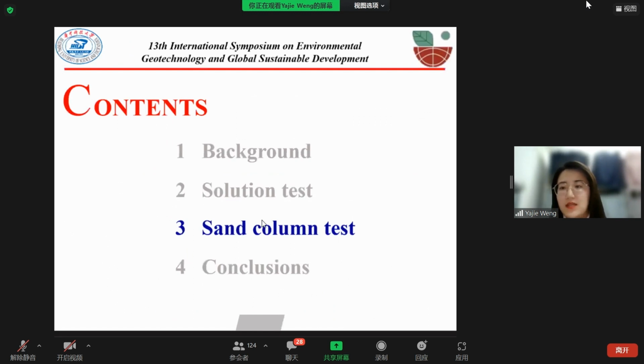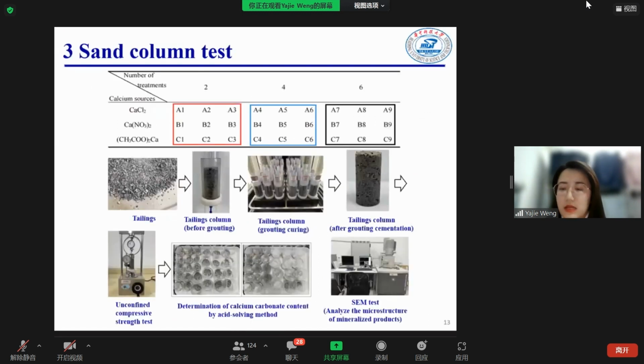The second is the tailings column test. The concept is to use the biocementing treatment solution with 3 kinds of calcium sources to cement the tailings and to study the influence of calcium sources on the strength growth law of the biocemented tailings. Samples were divided into 3 groups according to the type of calcium sources. The samples of each group were treated for 2, 4, and 6 times. The samples were in triplicate for all the tested conditions.